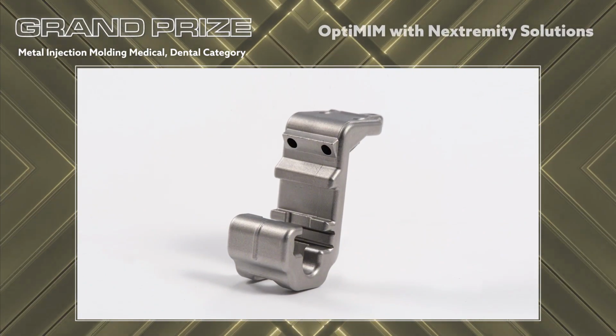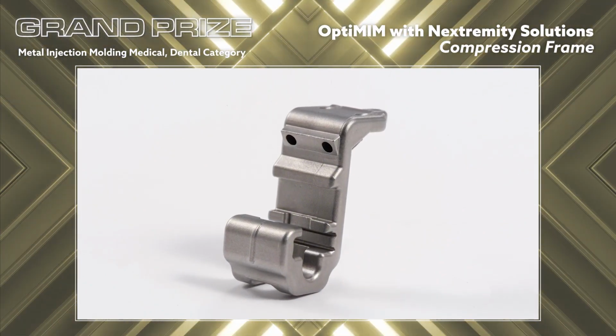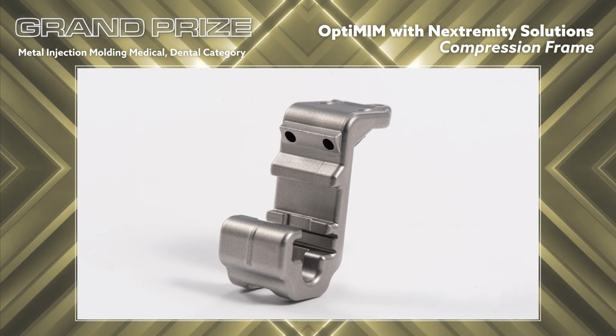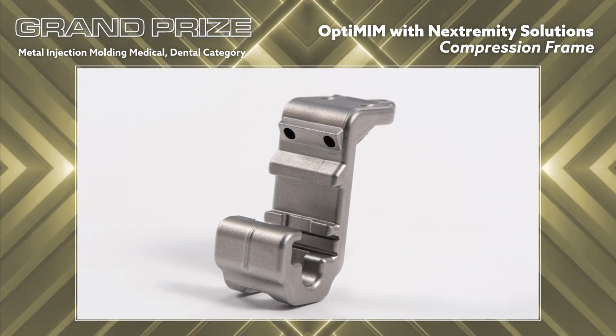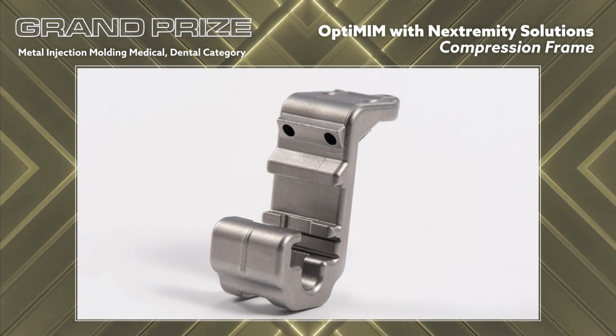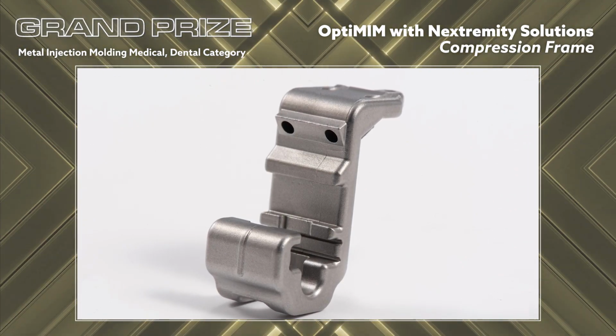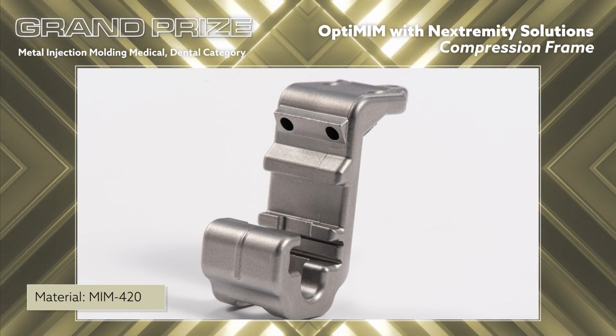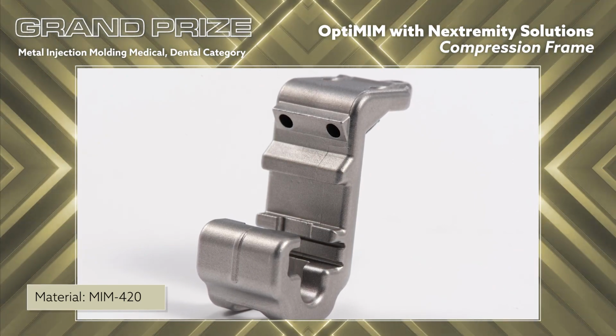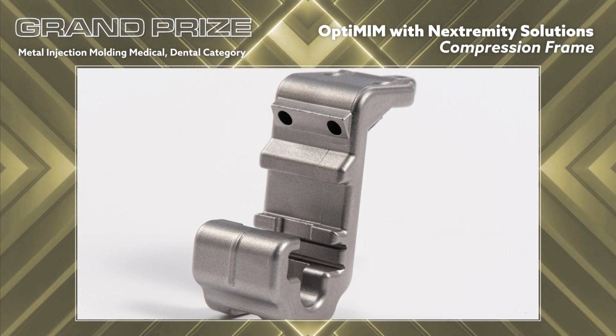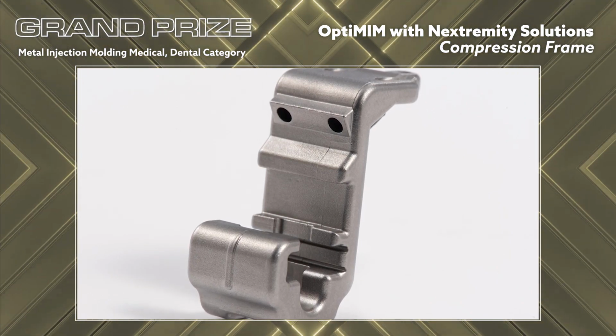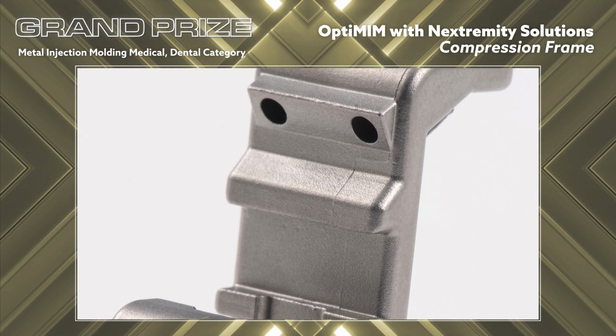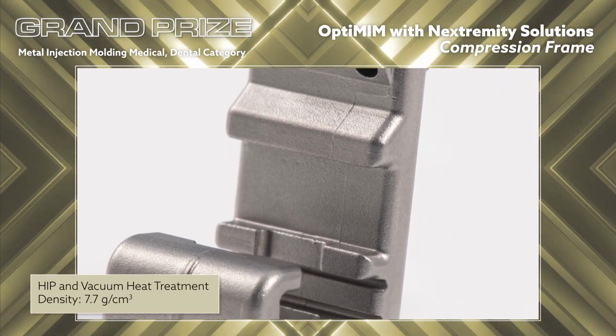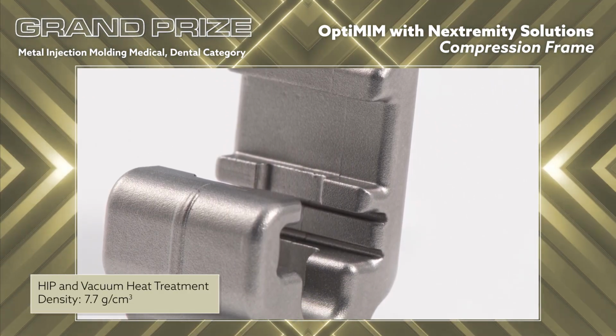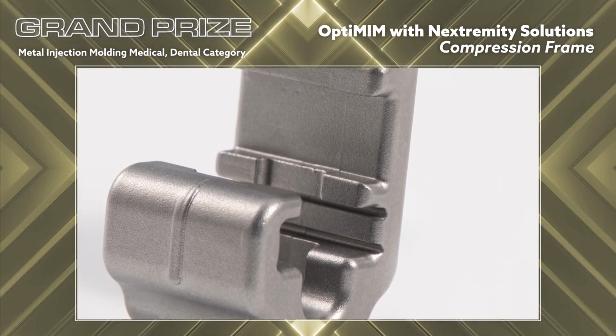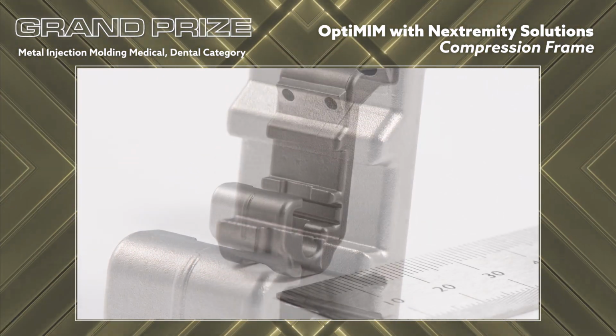In the medical dental category for MIM components, a grand prize has been awarded to OptiMIM for a compression frame used in Nextremity Solutions' Lapidus system for holding and aligning the targeting drill guide during tarso-metatarsal fusion. The parts are produced using MIM 420 stainless steel in a single cavity open and shut mold with 2 slides. The first forms the rectangular opening, and the second the 2 holes at 60-degree angle on the opposite end of the frame. Hot isostatic pressing is required to achieve an average density of 7.7 grams per cubic centimeter. After hot isostatic pressing, an annealing process is performed prior to secondary operations.